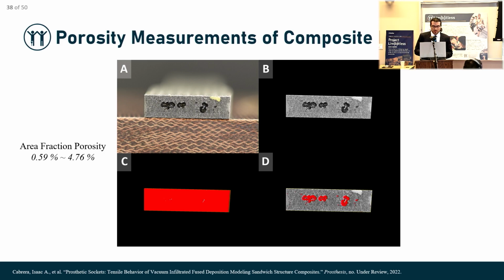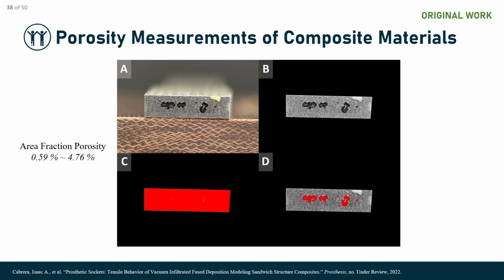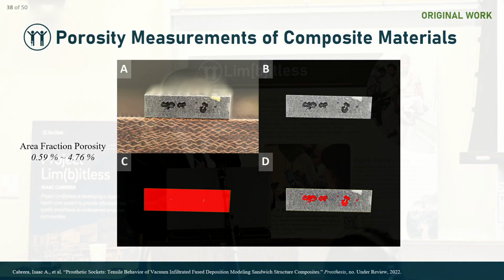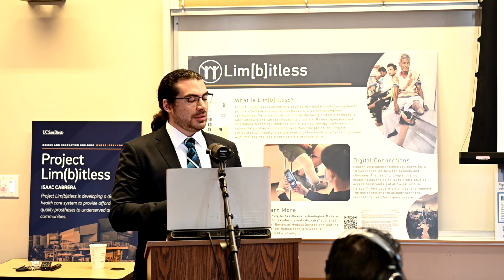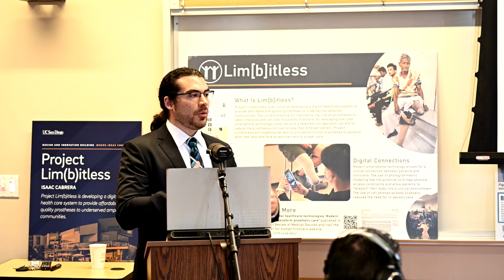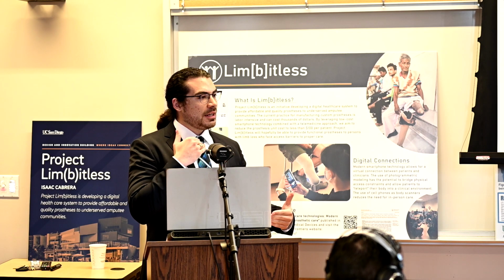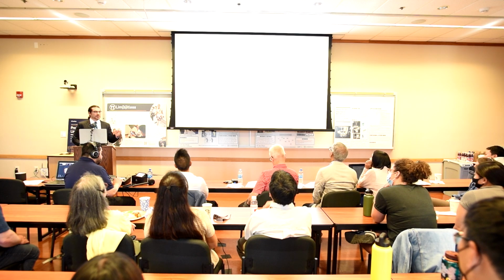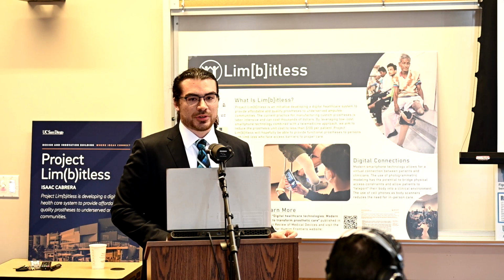Using ImageJ, I was able to quantify not just the area fraction of porosity, but also the average radius and diameter of all the porosity. Specifically for area fraction, it actually was less than anticipated, about 0.59% to 4.76%. So it wasn't so bad. It's quite low, but of course, there are different ways of addressing the manufacturing process to reduce that number, just because even a small percentage has such a big impact on our material properties.